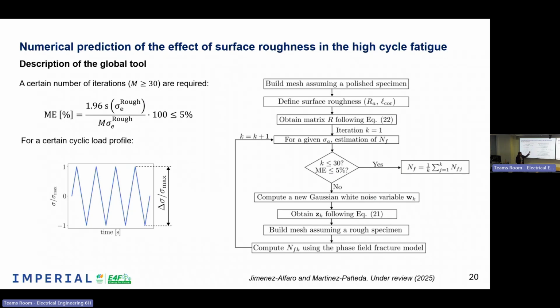And after that, we start an iterative procedure. So for a certain level of load, we compute a new Gaussian white noise, so one proposal for this randomness. We obtain the height deviation profile, we build the rough specimen with our tool, and finally we use the phase field model for fatigue to obtain the number of cycles to failure. We repeat this until we have a minimum of 30 specimens, and also our relative margin error is lower than 5%. Once we have that, our estimation of the number of cycles to failure will be just the mean of this distribution, and then we have the value.